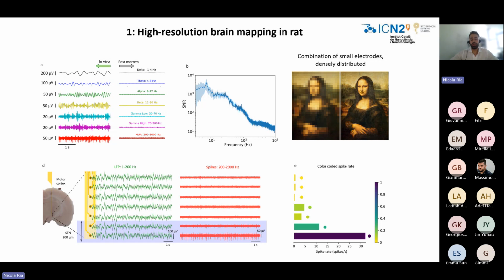On the other side, by looking at the local field potential, that is the kind of signal the large electrode can record, it is not possible to extract any information about the position of the lead, because the recording is quite similar through all the electrodes of the array. And finally, we have a color-coded spike rate, which quantifies the spike activity in the different channels of the array. And as you can see, the last two have much more intense activity, that are the two electrodes placed in the subthalamic nucleus.